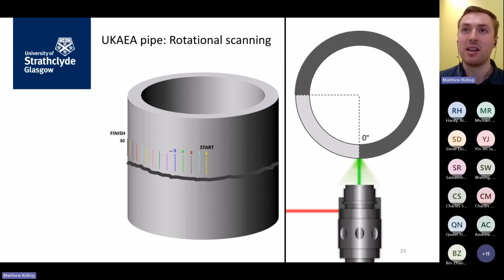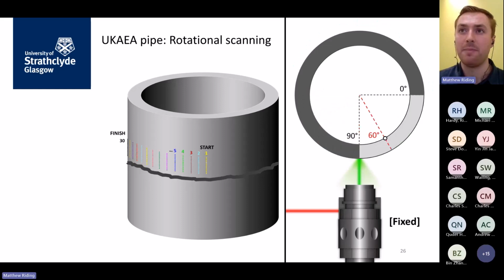And if we started at 0 and moved to 90, I manually positioned the defect, which I can see on the inner surface, at approximately 60 degrees into the scan, to give us something to look out for. We kept the lasers fixed, rotated the pipe on a rotation stand to complete the scan.